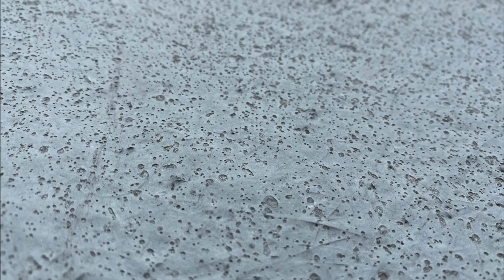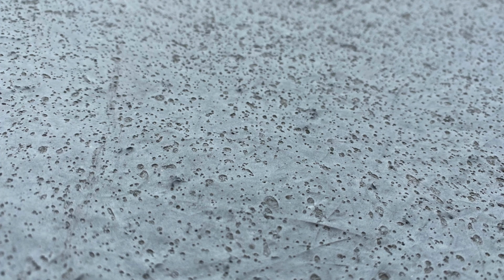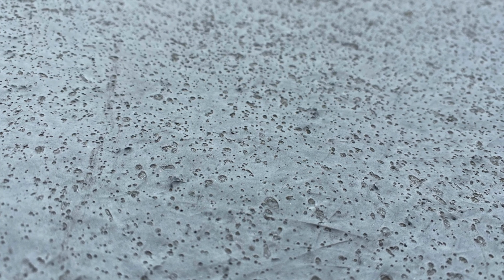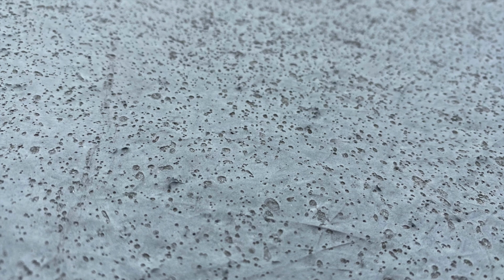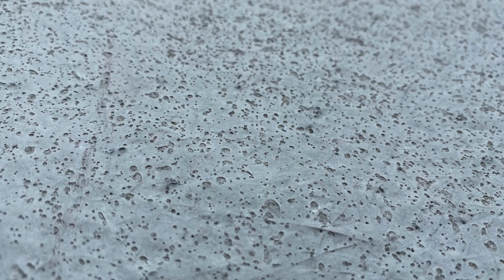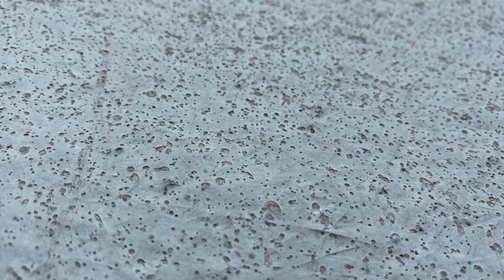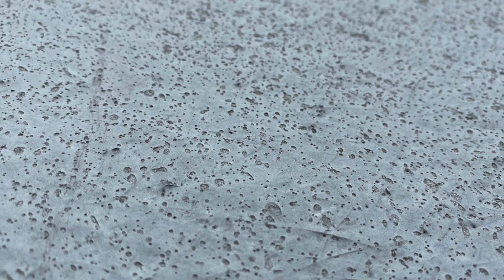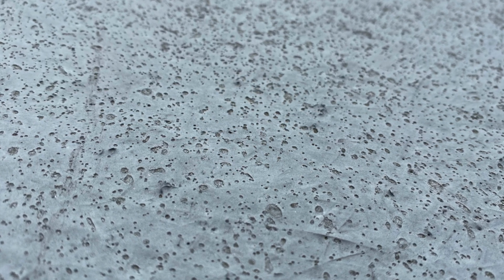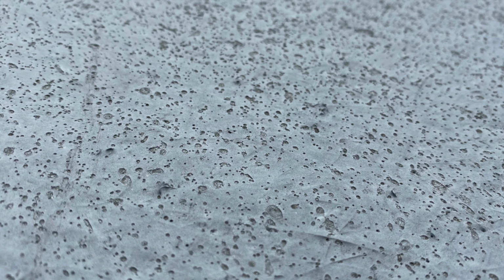We're showing these examples at this point before the top coat's been applied, because it means that you can prevent them happening to you when you're installing your own fiberglass roof. This example, it looks as though the top coat's either been applied during the rain or the underlying laminate has used insufficient resin, causing the top coat resin to fall into the air pockets that have been created.